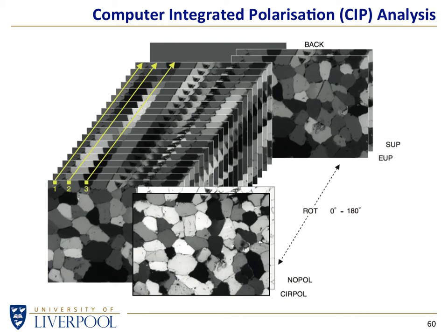We're not imaging the atoms, but the technique is sensitive to the alignment of atoms within the grain, because each alignment of a particular arrangement of atoms in a grain will result in a different variation of light, a different variation in brightness as the sample is rotated in a polarizing microscope.